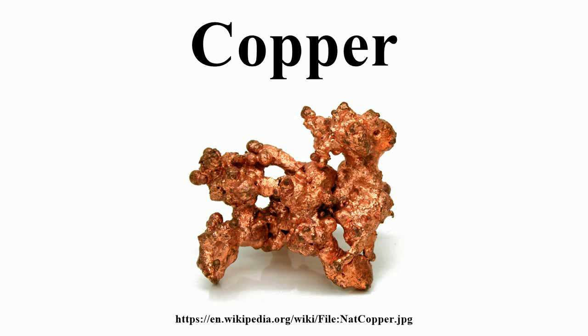This is because the resistivity to electron transport in metals at room temperature mostly originates from scattering of electrons on thermal vibrations of the lattice, which are relatively weak for a soft metal. The maximum permissible current density of copper in open air is approximately 3.1 × 10^6 A per square meter of cross-sectional area, above which it begins to heat excessively. As with other metals, if copper is placed against another metal, galvanic corrosion will occur.